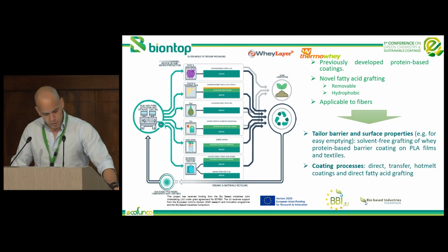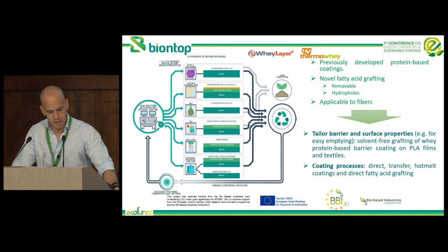For example, we are using novel fatty acid grafting to manufacture nanometric layers, which, in spite of being applied to multi-layer films, can be later removed and do not affect their later recyclability or their biodegradability. The hydrophobic grafting contributes to reducing product waste at end of packaging use through a release easy emptying effect.